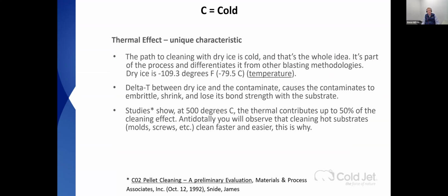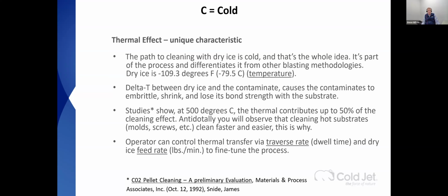Studies, once again from James Snide's library reading materials, show at 500 degrees C, which is not likely to happen in the molding world, but thermal properties contribute up to 50% when the mold is hot. Anecdotally, you're going to say, man, I've cleaned things hot. They seem to clean better and they seem to clean faster. This is why. The thermal effect is contributing more on hot substrates. So that rule of thumb, if you get a chance to clean it hot, do it.